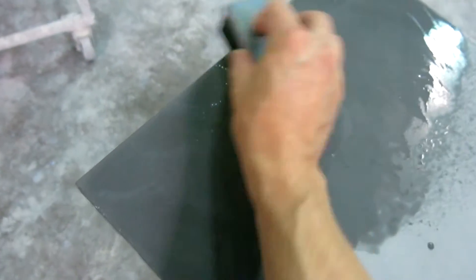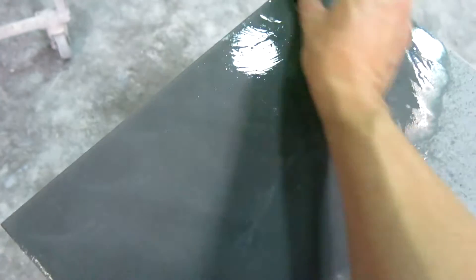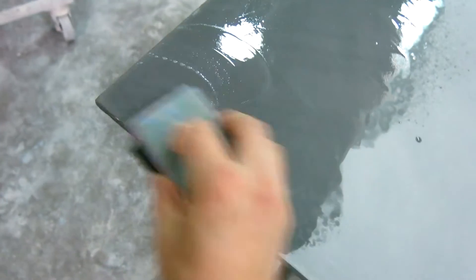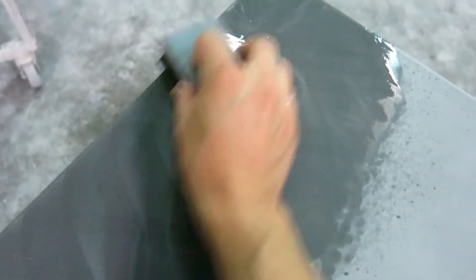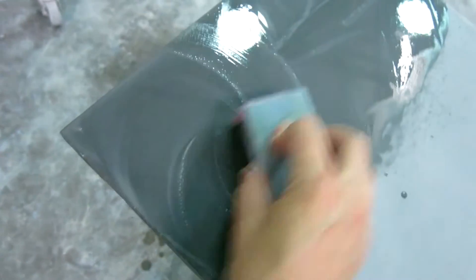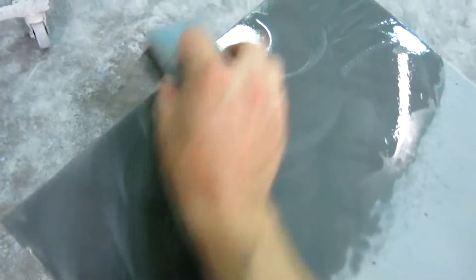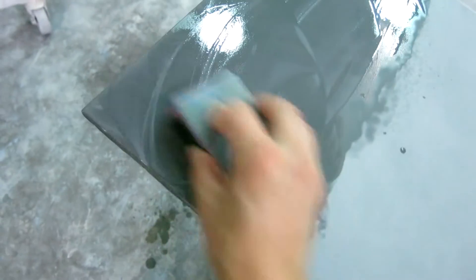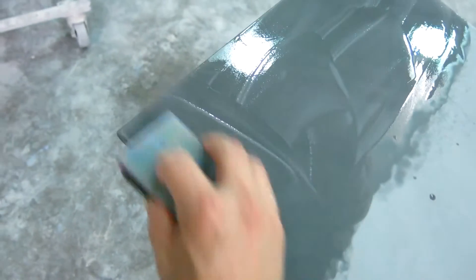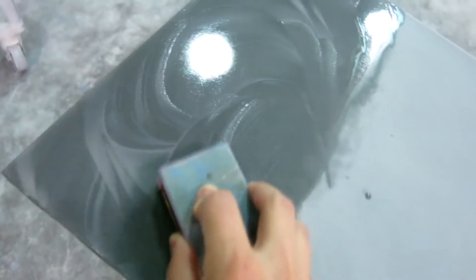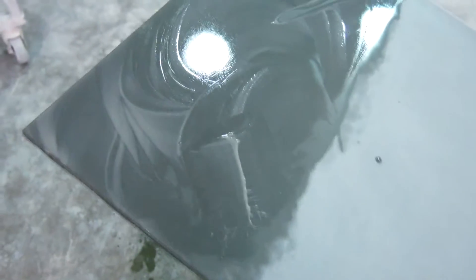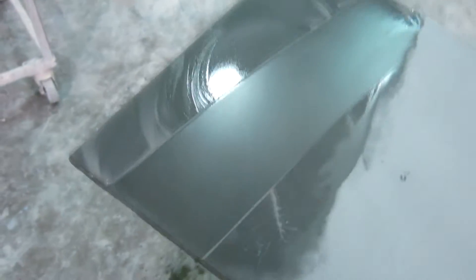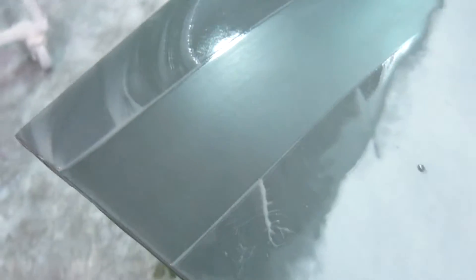You get the idea. So if you want to keep a cream finish, this is a good way to prepare the surface and keep the same look. If you're not getting rid of the cream surface, all you're doing is cleaning the surface, you're removing the surface texture of the melamine and any residue, if there's wax or anything like that that might have transferred to the concrete, that's coming off too. So you can see there's a little bit of slurry coming off, a little bit of cuttings. I'm going to use the same diamond hand pad to clean it off.